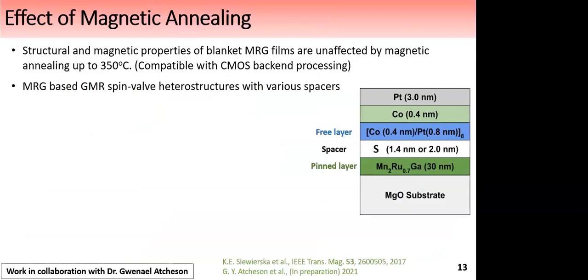So first, looking at the effect of magnetic annealing. So one part was just annealing blanket films up to temperatures of 400 degrees C. And what we find is that annealing up to 350 does not strongly affect the films, and this is compatible with CMOS backend processing. Then we've also prepared GMR spin valve type heterostructures where I'm showing a stack diagram on the right-hand side, and they were also annealed in a magnetic field at 350 degrees C.